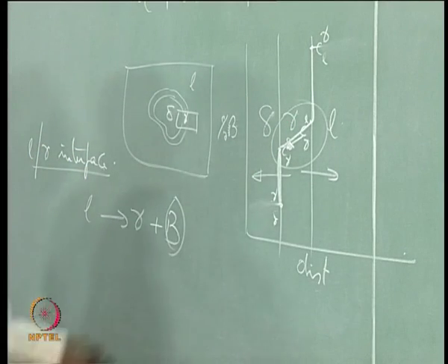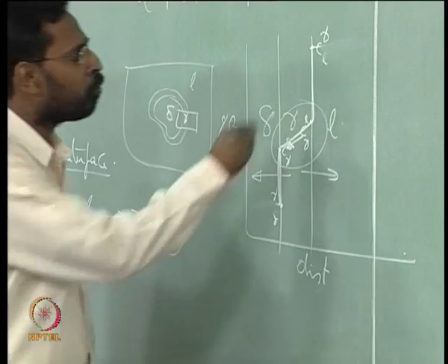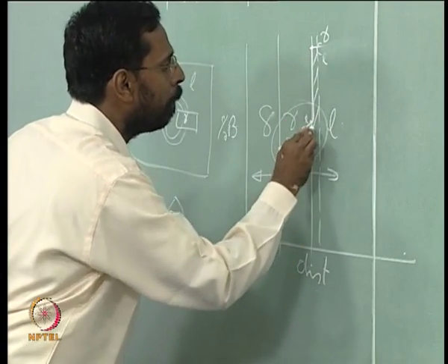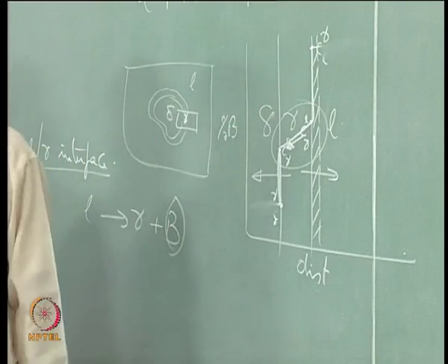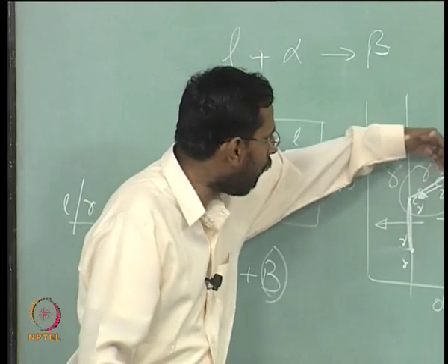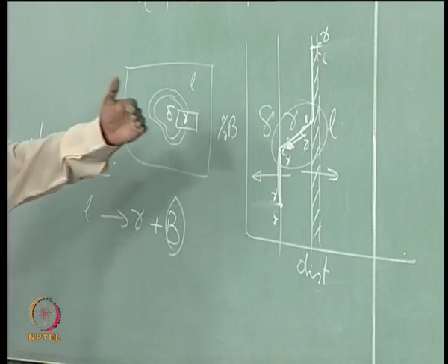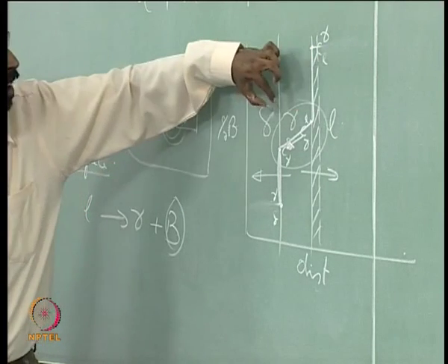And now what happens is, once these B atoms reach this, before that, what has happened is that a small volume of liquid, a small delta x of liquid, has got converted into gamma of the same composition as that of gamma, and whatever excess B atoms the liquid has, it has rejected them out, and those B atoms have started moving towards the gamma-delta interface, and this small region has got converted to gamma.